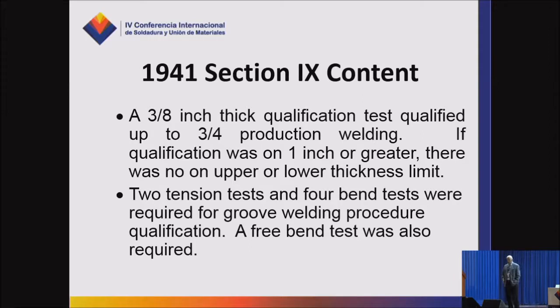Back in the good old days, a 3/8 inch thick qualification test piece qualified the production weld up to 3/4 of an inch in thickness. Well, what we see here is what most of us that deal with the code are familiar with. It's the 2T rule. If you qualify a procedure using some test piece that has some thickness, you're usually qualified for twice that, kind of rule of thumb.